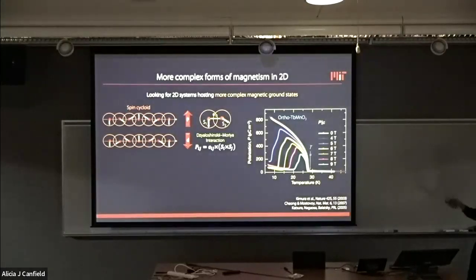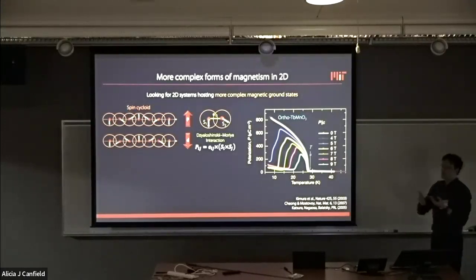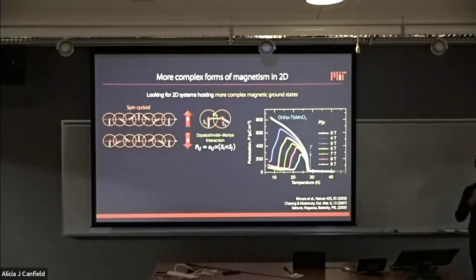It was compared to the original discovery of type 2 multiferroics, so multiferroics where the ferroelectricity is improper. It's driven by electronic effects such as spin-orbit coupling, and it's due to the fact that you have a spin structure which breaks inversion symmetry. So it's very much like a spin-induced ferroelectricity.